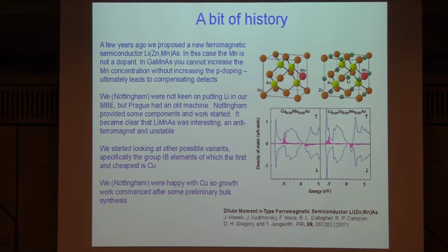So when we started realizing the limitations of the material, we wanted to look for an analog where this wouldn't be the case. And we came up with this material, lithium zinc manganese arsenide, which in this case is a 125 semiconductor, and the manganese of course then goes substitutionally, so it's not doping anymore, so you don't get this solubility problem. So we thought, great, this is a great idea. It even fits nicely on gallium arsenide.